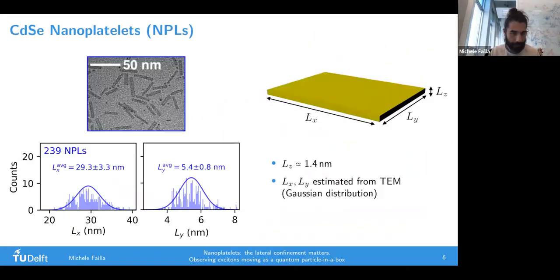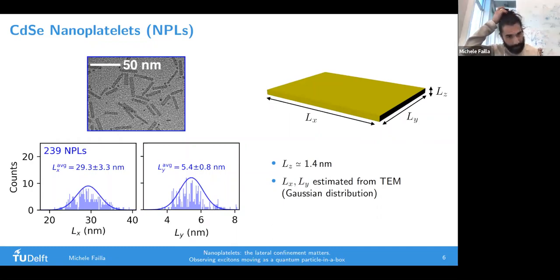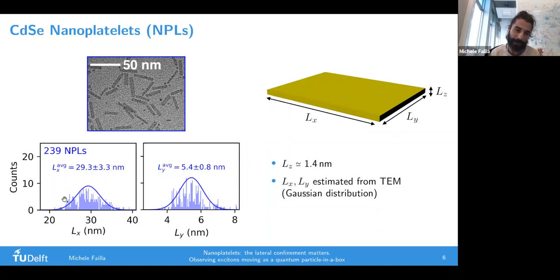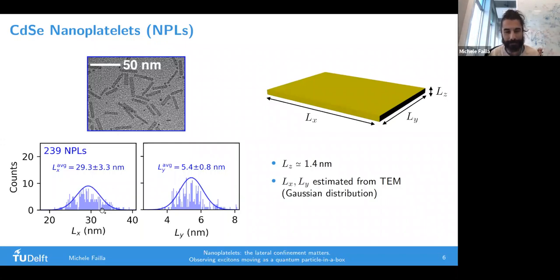Now we go to the main topic of the talk - cadmium selenide nanoplatelets. Here is an example of a TEM image of one of the samples. You can see they are really like flakes - they are called nanoplatelets because of their shape. After preparing a sample, you take TEM images, count all the nanoplatelets, and measure all their sizes. You then consider the resulting size distribution, which distributes in a Gaussian way. You perform a Gaussian fit to get the average size for the lateral dimensions LX and LY.